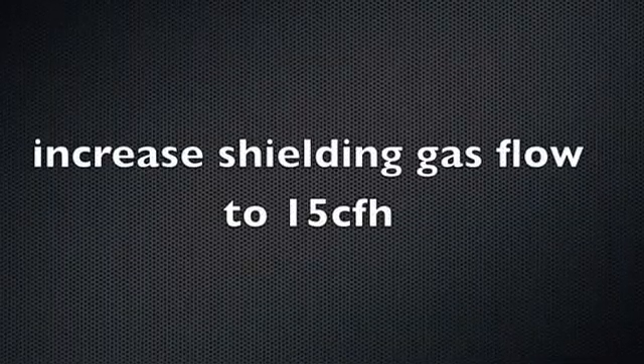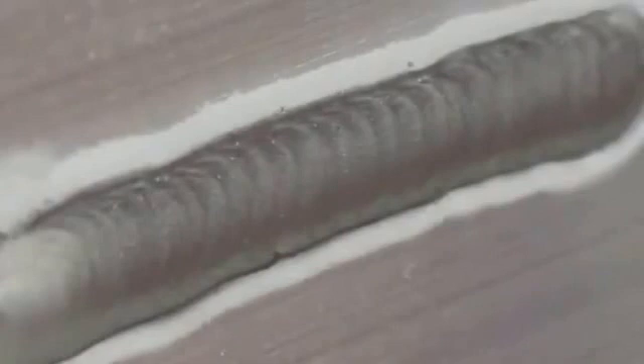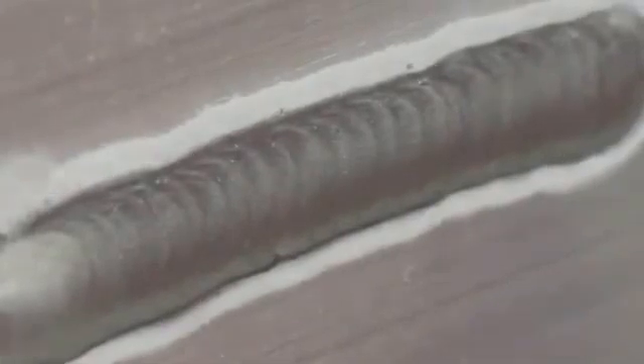So I increased it only 5, just to 15 CFH, and now you can see during this arc shot here, I've got a good band of cleaning action on the bottom as well as the top, as well as in front of the puddle. That's much better. It's welding much cleaner. Everything's going much better. You see the band of cathodic etching on the top as well as the bottom there. That's what you need.